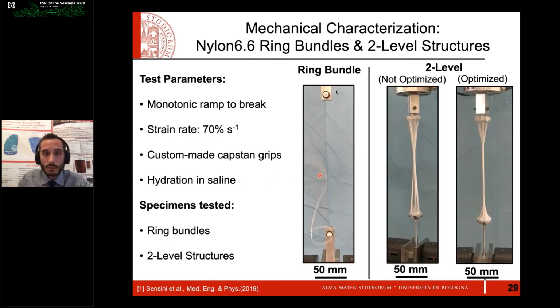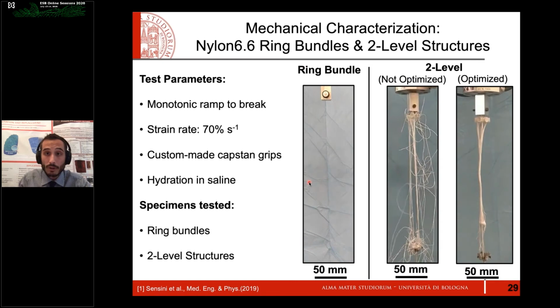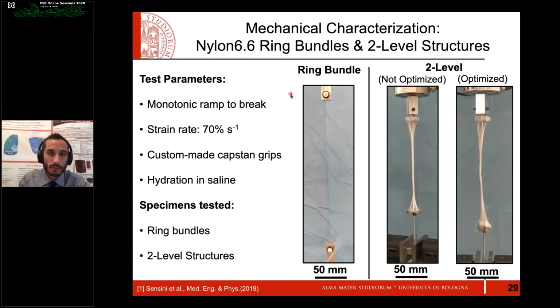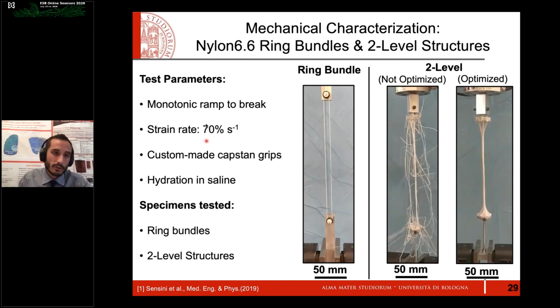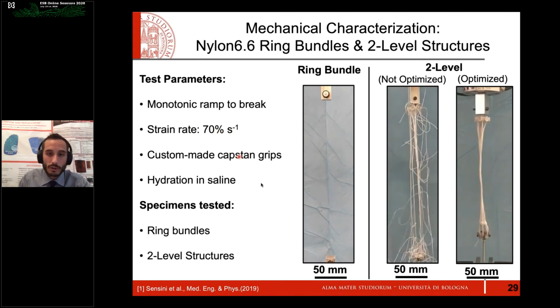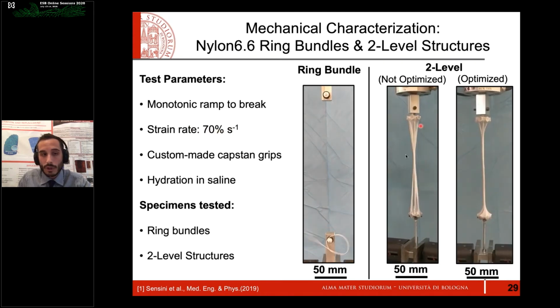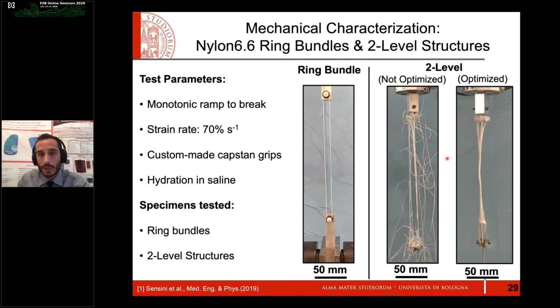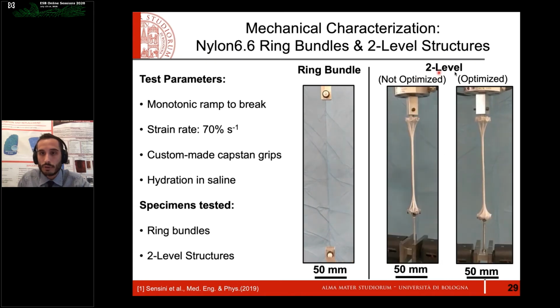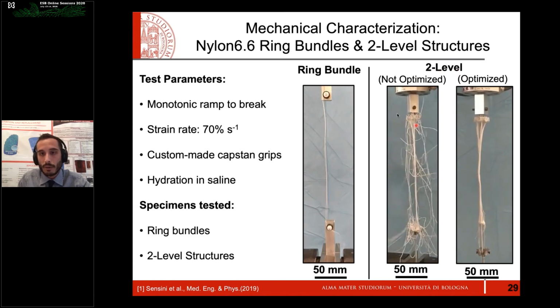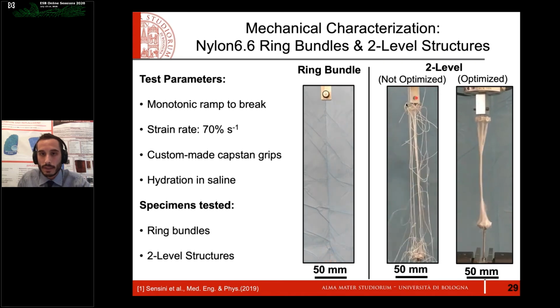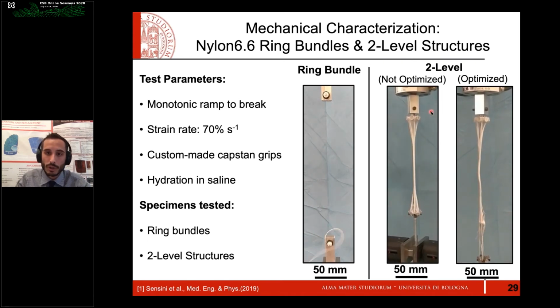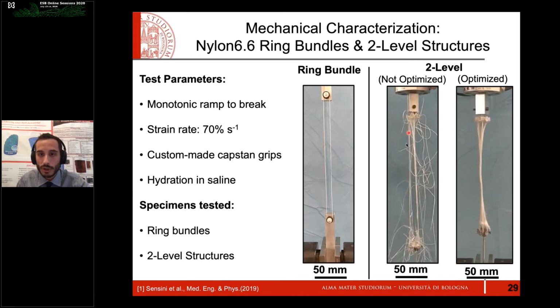We also tested the ring-shaped bundles and two-level structures in nylon 6,6, using a 70% per second strain rate. What you can see from this slow motion video, particularly for the two-level structure, is that we first developed dedicated helical capstan grips to try to reduce as much as possible the stress concentration.